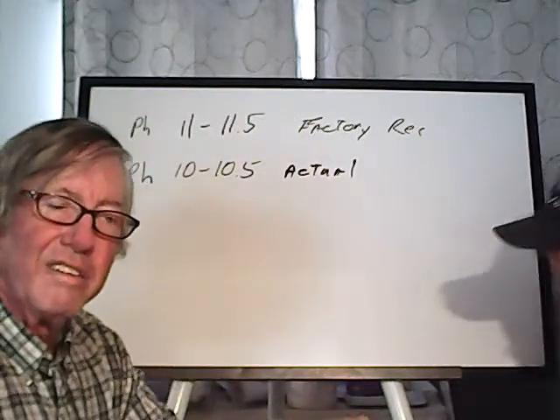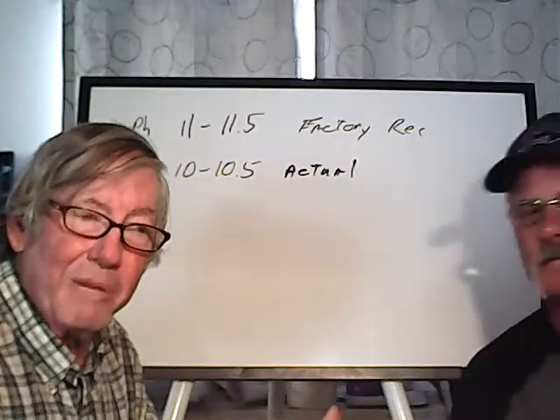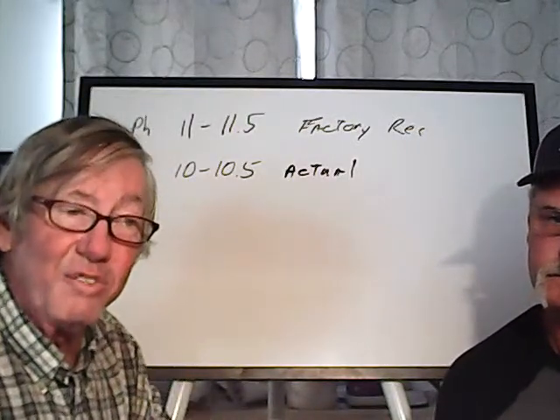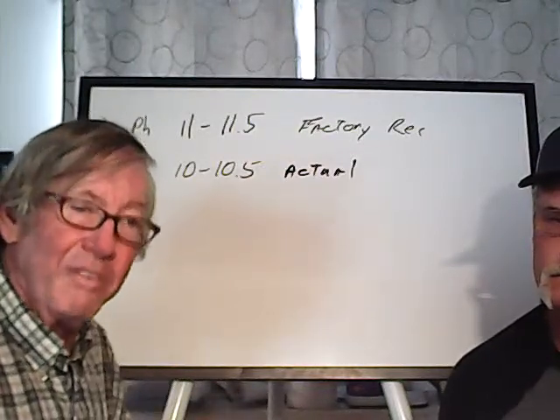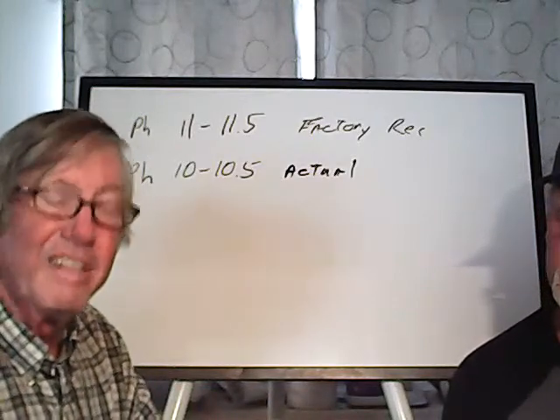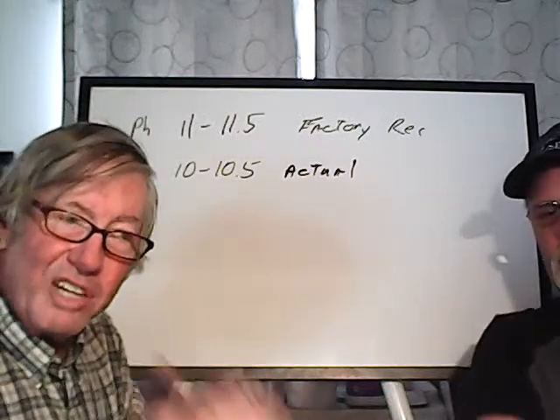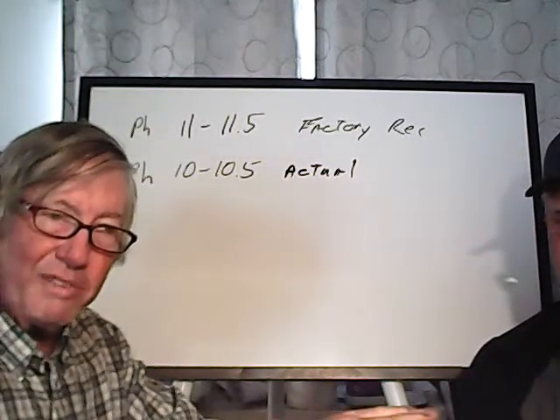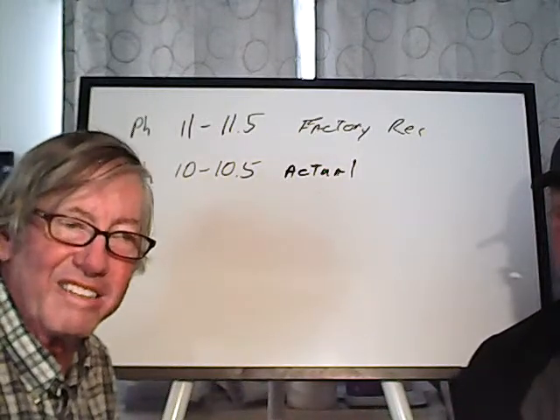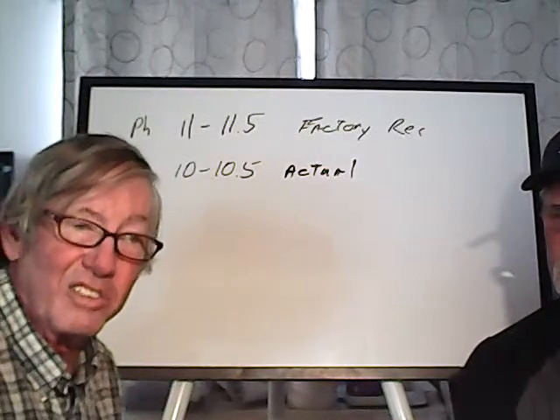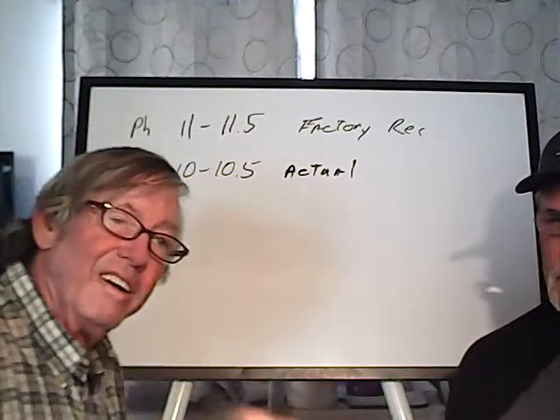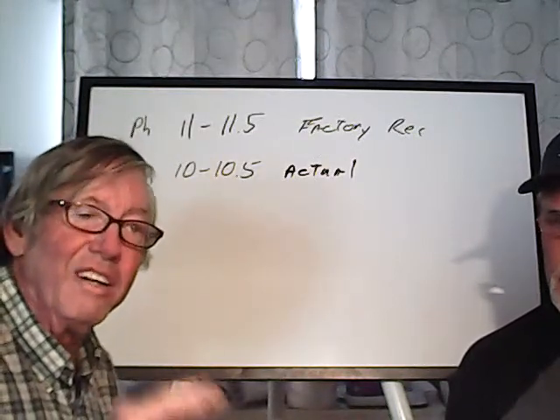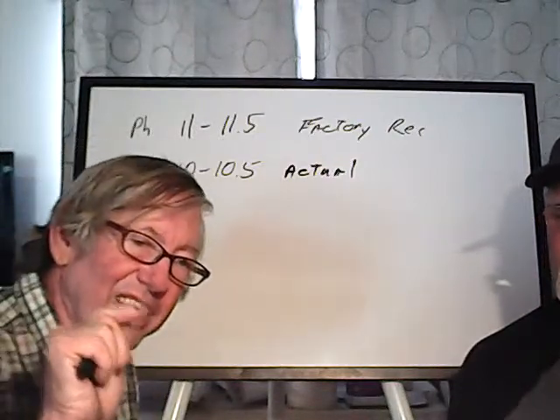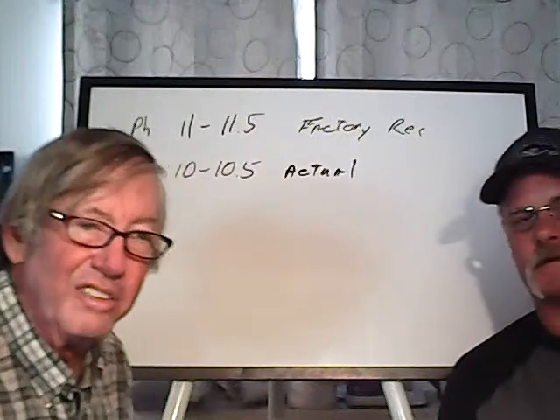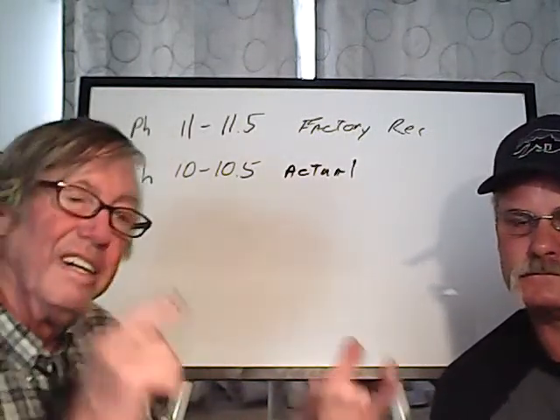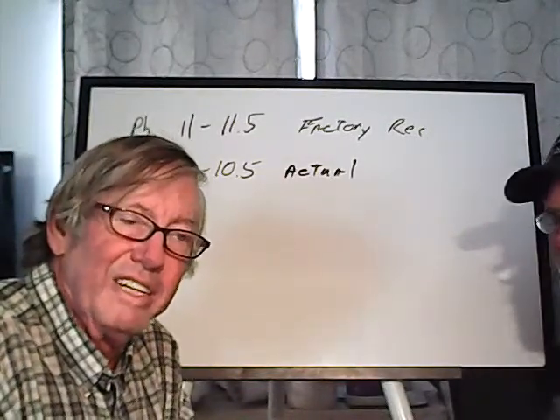And test, crush it. I would just start out panning it, okay, because it's real cheap. And it's actually a fairly efficient gravity separation technique, especially if you pan it a couple of times. You pan it and then pan your tailings and then pan the tailings again. Take those concentrates and the tailings after you pan them and have them both assayed, have them both analyzed at a laboratory, and that'll tell you where your various metals are going. If the vast majority of the metals are in the heavies, then you've got a real easy way to concentrate it. And then you're trying to get the gold out of those heavies. That's a lot easier to do than out of the slag. The slag itself, if you melt it, it takes an enormous amount of energy. Yep. It takes a lot of heat.